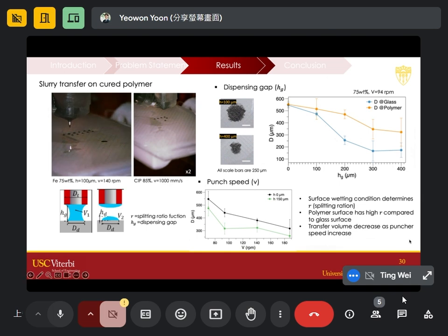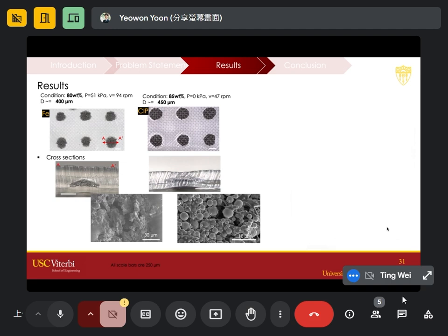Okay, and then these are the videos of the magnetic slurry punched on the elastic resin we're printing. Once that's done, the laser is going to cure it, and then we're going to print another layer on top. So that's two different materials printing on the substrate. Look at the results here. This is basically a sandwich structure: resin, polymer, and then magnetic slurry and polymer.